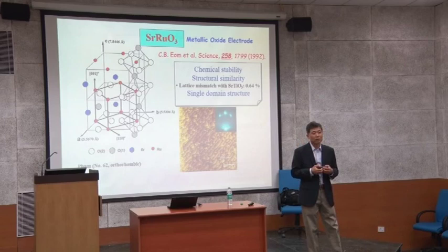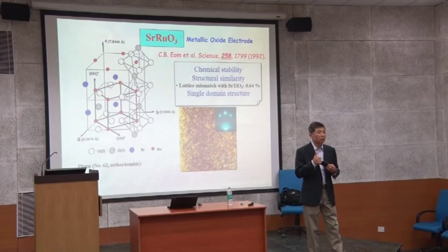Proper substrate too. So what kind of proper substrate do you need? A 1-1 orientation substrate. Okay, you're getting close, 1-1 substrate. But when you grow on a 1-1 substrate, your film grows in the 1-1 direction. So that means you want the 1-0-0 direction, not the 1-1-1 direction. You want to grow in the 1-0-0 direction. Okay, so getting close.